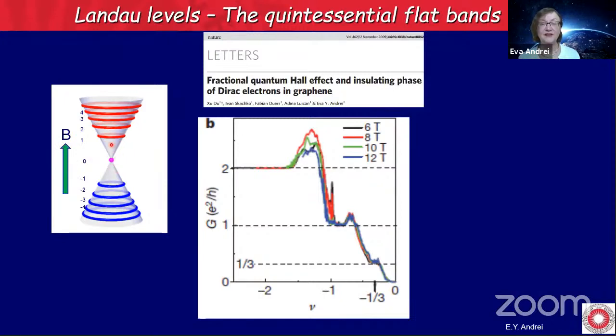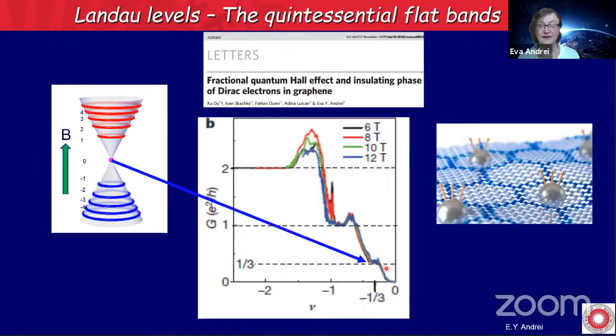And by bringing the Fermi energy into these Landau levels, indeed, you create strongly correlated states, in particular the fractional quantum Hall effect. This is from our 2009 paper, where you create a plateau at one-third filling, which means that for every electron, you have 3 flux quanta that penetrate your sample. So this creates a sort of composite particle where every electron grabs 3 magnetic flux lines and moves around with it, and that gives you what we call a quantum Hall plateau that is seen in the Hall conductivity.